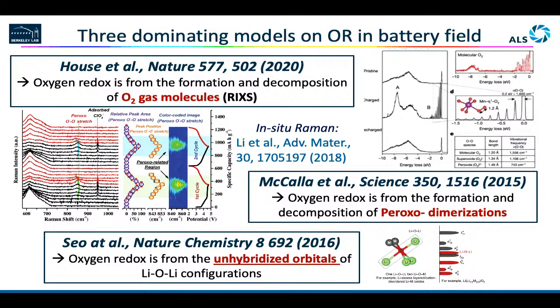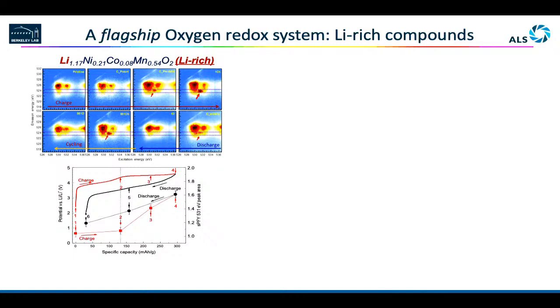Anyway, when we look at all these three dominating models, there are two things we see. One is they are all talking about an unhybridized oxygen bonding formation, either it's oxygen gas, or it's peroxo species, or it's a pulled up unhybridized oxygen state. When you oxidize, they also form dimerization or form gas molecule. And two is all this relies on specific structural configurations to have or not to have. It essentially tells us this is not a common or universal behavior that you are expecting from all kinds of transition metal oxide material. So let's see whether these are true.